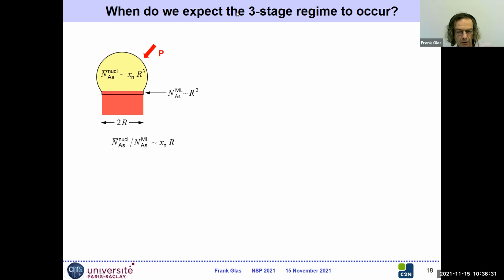So we expect to be in this three-stage regime where we do not have enough arsenic atoms in the liquid at nucleation to form a full monolayer, when the ratio of these numbers is less than 1. So the ratio scales as the product of this characteristic concentration and R, the radius of the nanowires, which means that we expect to see it for small nanowire radii and for small concentrations, which probably means low growth rates.